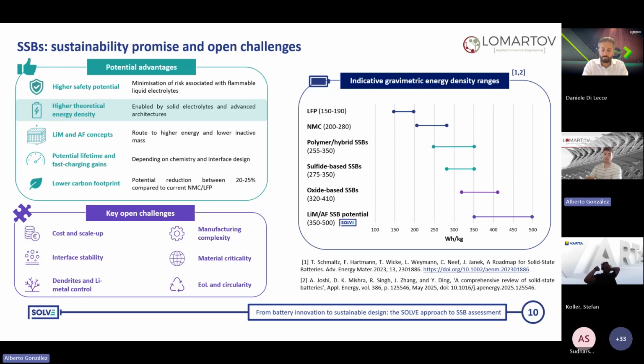In the second place, we have the interface stability. In a liquid battery, the electrolyte can wet the electrode structure, but in the case of SSBs, the ion transport depends on the solid-to-solid contact, and if this contact is poor, the interfacial resistance and the degradation can limit the performance of the battery. Third, we have the dendrites and the lithium metal control. Lithium metal is one of the routes to higher energy density, but if the lithium plating is uneven, or there are local current hotspots or defects in the electrolyte, it can still lead to short circuits or accelerate the degradation of the battery.